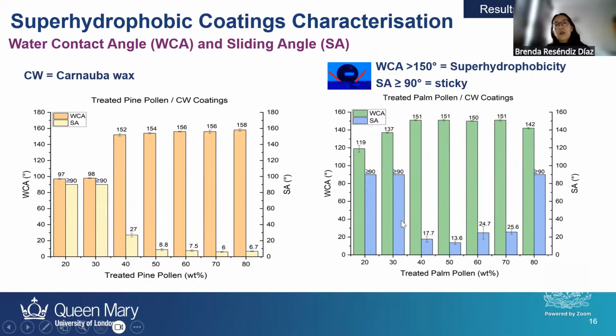In the case of palm pollen, it was more in the middle: between 70 and 40% weight percentage, I have a contact angle above 150 and sliding angles between 20 and 17. And when I increase the amount of wax, again I'm reducing the contact angle because I'm getting a flatter surface, as if the wax is covering more features of the pollen.